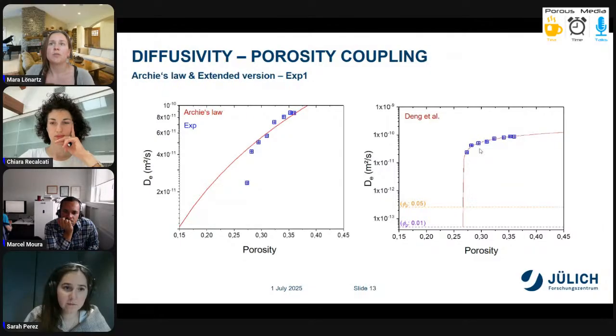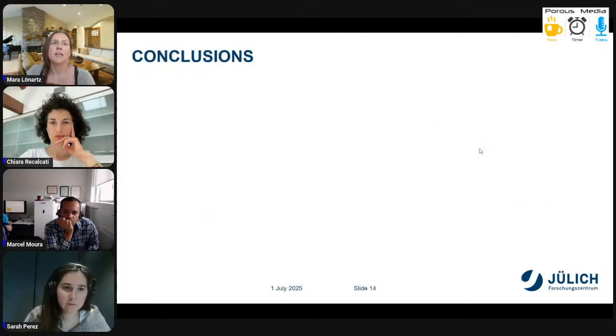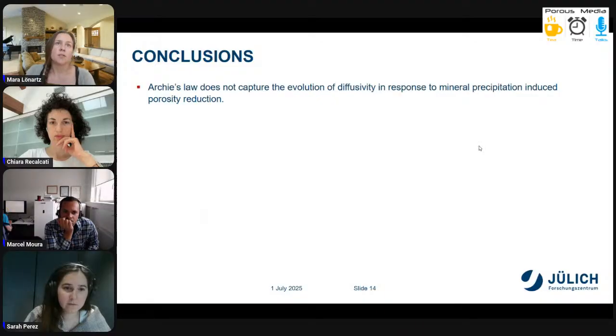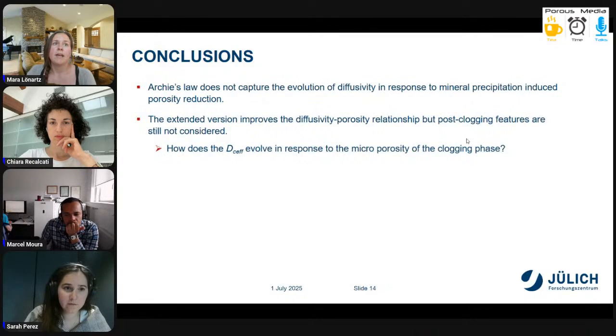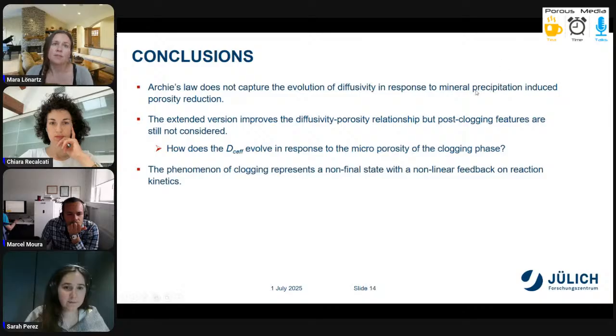Which brings me to the first conclusions I could draw on this little project. We can say that Archie's law does not capture the evolution of the diffusivity in response to mineral precipitation reactions, and that an extended version improved the description of it, but post-clogging features are still not considered. So the still open question is what actually happens with the critical effective diffusivity if we think about, again, the redissolution and reprecipitation. Is there maybe a second state of clogging? And with this, clogging represents a non-final state with a nonlinear feedback on the reaction kinetics.